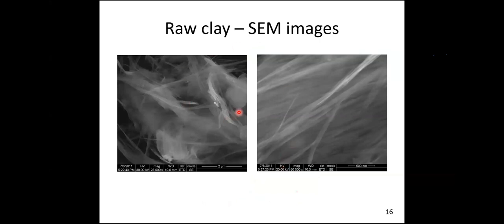Again, this is a typical scanning electron micrograph of raw clay at different magnification. It is at low magnification around 23,000x, whereas here it is 60,000x. It is not dispersed with epoxy, it is just a raw clay. I just wanted to show how a clay looks. If you see carefully, it looks like a layer. It has a nano size thickness and micron size lateral dimension. So basically it is a layer, like a paper. This is what we could see from the micrograph.